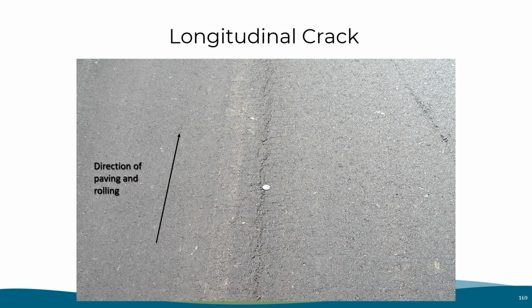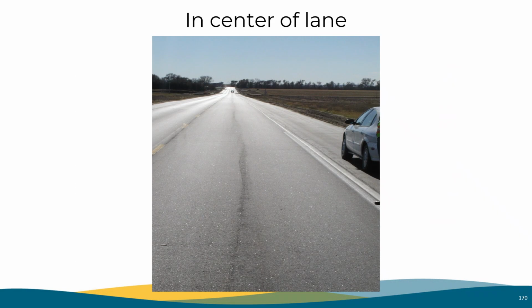You can also experience a longitudinal crack in the direction of the paving and rolling from over-rolling the tender zone. Mostly, you will see this in the center of the lane. This is generally because the contractor didn't overlap the rolling. This can lead to obviously poorly compacted sections of the pavement and ultimately leads to poor pavement performance.